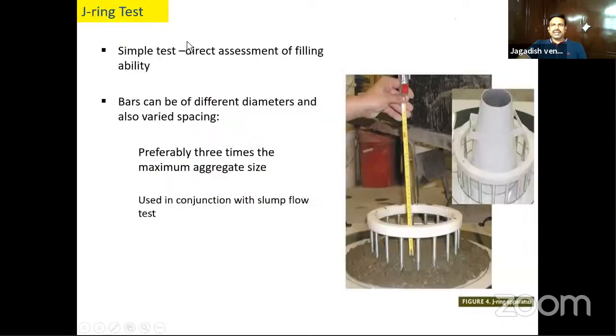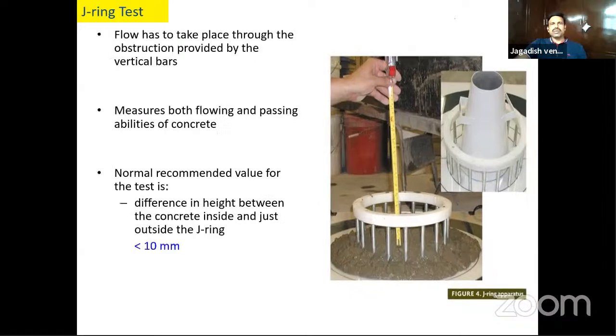That's how you measure. Next, there is also a test called J-ring Test. So this is a simple test. You measure the filling ability and a little bit of passing ability. You have a ring with the reinforcement. At the middle, you place the slump cone. You pour the concrete, you lift the slump cone. And the concrete also passes through this J-ring. So you measure the height difference between inside J-ring and outside J-ring, because it passes through the reinforcement. If the mix is having a problem, you find more height in the middle because it won't pass through. So the height difference between inside and outside of the J-ring should be less than 10 mm. This is how we measure the J-ring test.